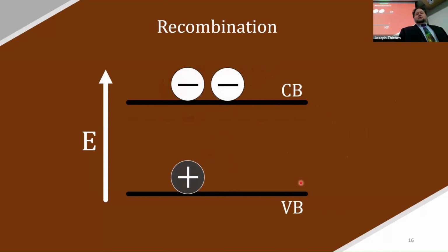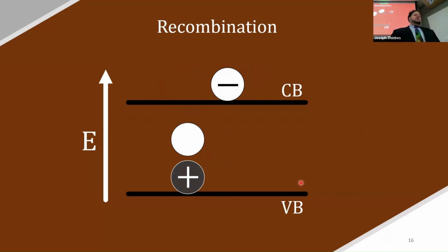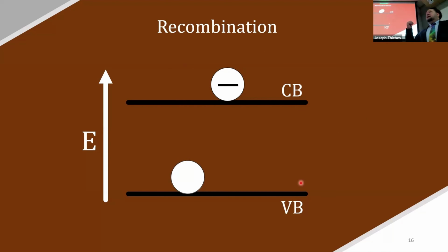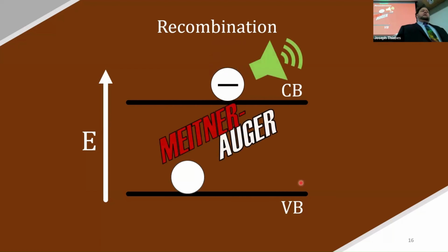There's a third way, which doesn't happen generally unless you have a lot of excited states close to each other. That's when the electron recombines with the hole, and instead of emitting a photon or putting thermal energy into the material, it puts that energy into another excited state and bumps it up a little bit higher, still within the same band, and then it drops back down to the band edge immediately. That's called Meitner-Auger recombination. And that little bit of energy usually goes into thermal energy.